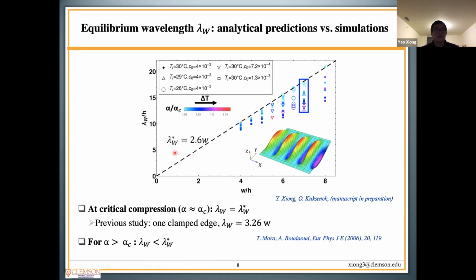Here, we summarize the wavelengths of buckled samples from 5 series of simulations, and the data corresponding to samples in the previous slide are marked by the box. The samples at the critical points in each series are in light blue. We found the wavelengths of those samples show very good agreement with the analytical prediction. In the previous study, where gels are clamped at one edge, they found the wavelength also linearly depends on the sample's width. Above the critical point, the wavelength of buckling becomes smaller than the analytical result.